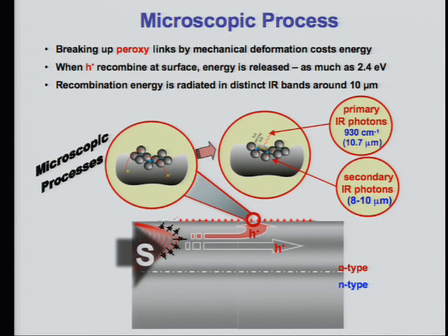And the only way for these excited atoms to really thermalize and come back to ground level is to shoot off photons. And these photons should be equivalent to the energy spacing of their vibrational manifold. And we know that. There are high-level quantum mechanical calculations for this bond in fused silica, because this defect is actually of great interest to the optical fiber industry.